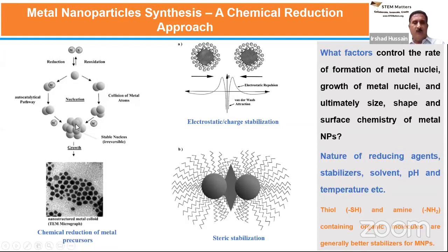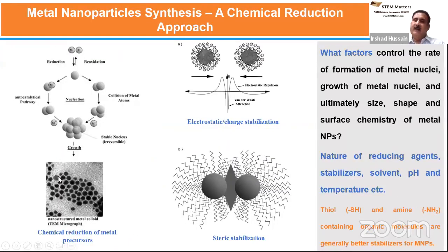But if we let them grow for some time in the presence of weak stabilizers, then they will grow depending on the nature of that stabilizer and the nature of reducing agent to make bigger particles, nanoparticles, in fact. And so these particles, if you carefully look at them, they are smaller than 100 nanometer. So that means they have huge surface energy. So in order to minimize their surface energy, they tend to agglomerate, and you really need to use stabilizers which can prevent the aggregation of these nanoparticles into macroscopic materials.